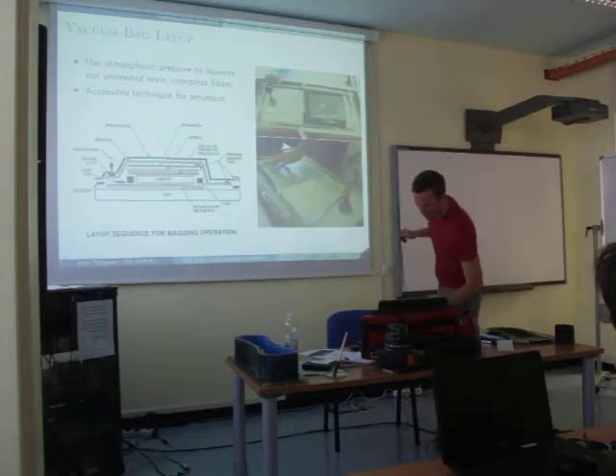These are the 4 layers of the vacuum bag technique that we're going to see next. It has a green vacuum bag, which is the sealant, keeps an airtight seal between the part and the atmosphere. There's a bleeder ply, which absorbs extra resin. There's a release ply, which is pink and has little perforations through it so that the resin can flow through. And then there's a peel ply, which can be against the part if you expect to be doing a multi-step layup. You put this peel ply on there, and then you pull it off after it's cured, and it leaves a textured surface. That textured surface can be better for bonding to.